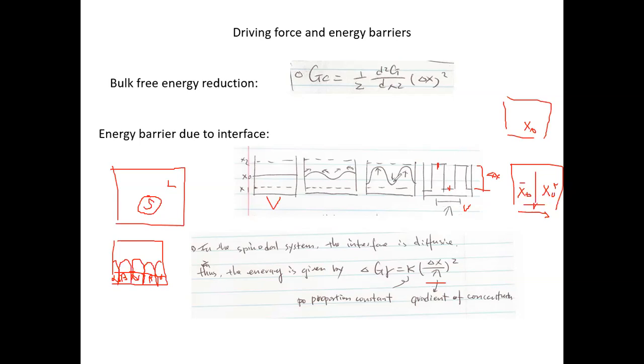It's quite clear to see at the end, but even in this case we can define it, and lambda is basically the wavelength between this peak and this peak. You can consider lambda to characterize the distance over which your composition drops from the peak to the valley. It's one half of lambda, but basically on the same scale of lambda. And the drop of the composition we define to be delta X. So if we use delta X over lambda, this provides a rough estimate of the sharpness of the interface, or how fast things change over a small distance.